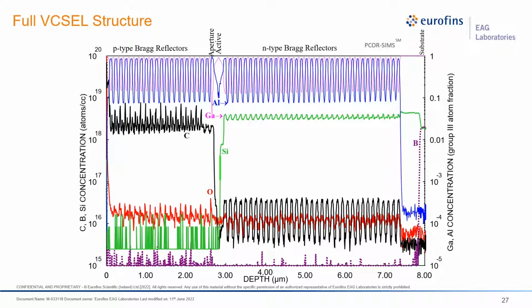You can see in this slide that plotted to the left axis are the carbon, boron, and silicon concentrations. You can see the carbon in the top P-type DBR and the silicon in the bottom N-type DBR along with oxygen impurities. And the boron is simply to mark the substrate interface.